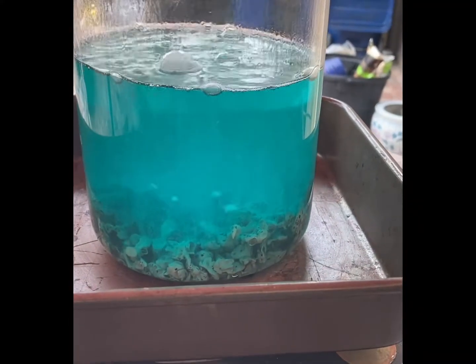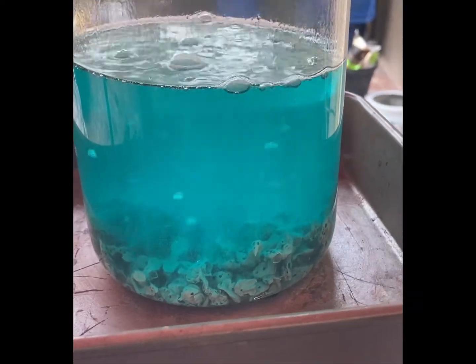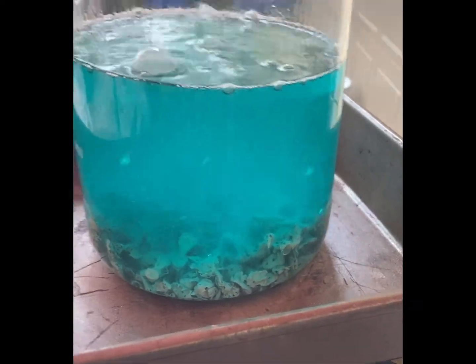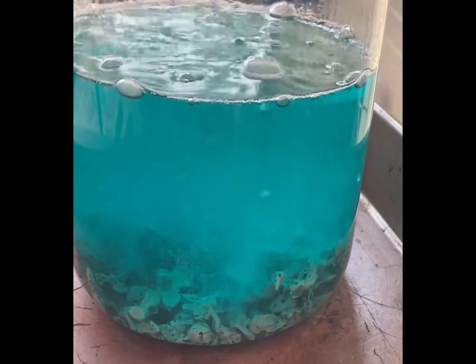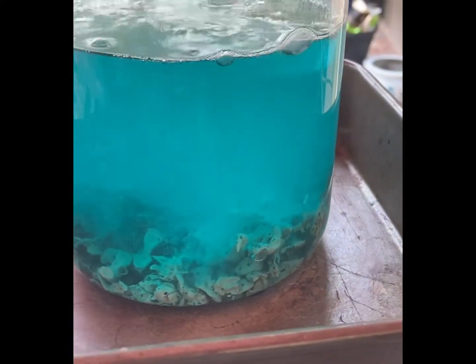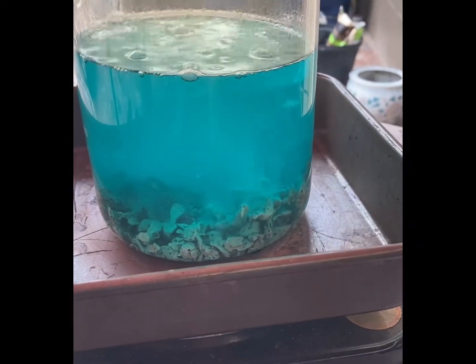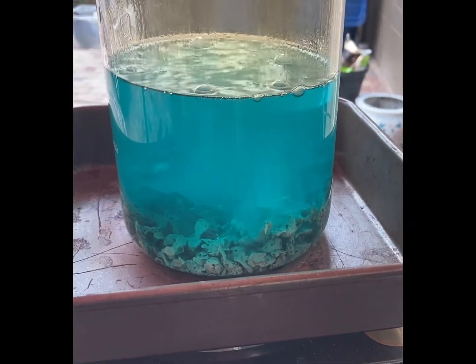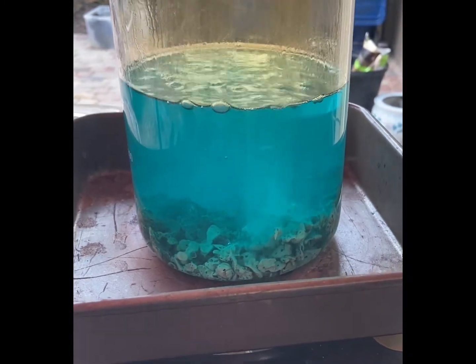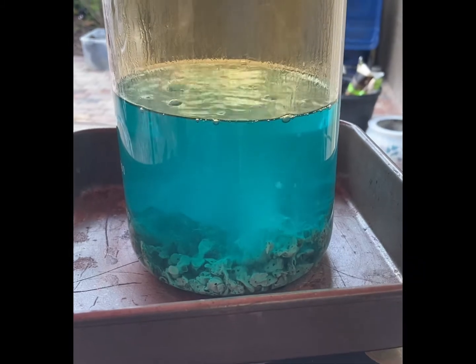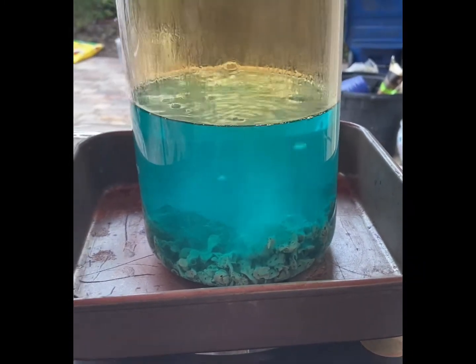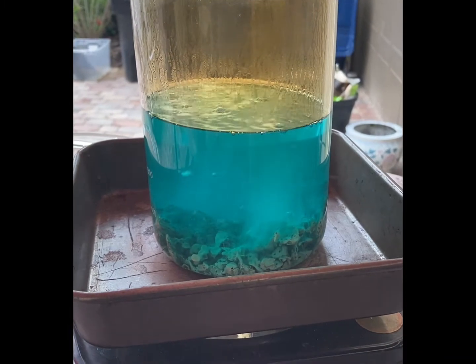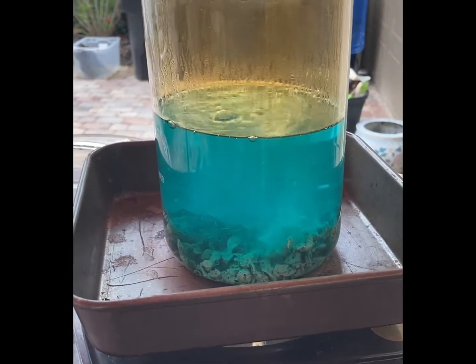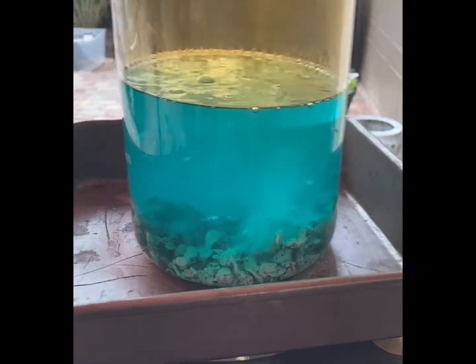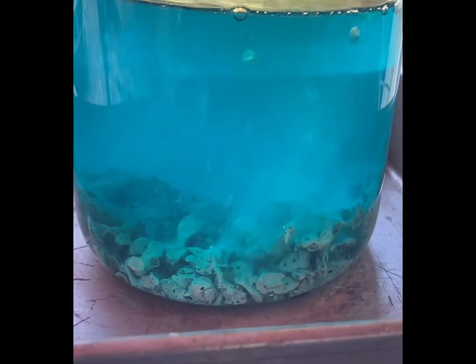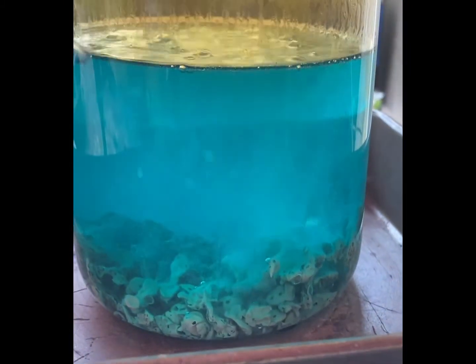Just put in another 50 milliliters. You can see how clear and clean that silver nitrate is, what it's developing into. And that's because this is a double refined silver nitrate. So there's very little impurities. This is probably 98%. Maybe a little bit less, because like I had mentioned, I had some contamination when I did my shot, either from the crucible or from the water. So running a second refining is definitely going to come out looking really clean and pure. But I love how clear that silver nitrate is.